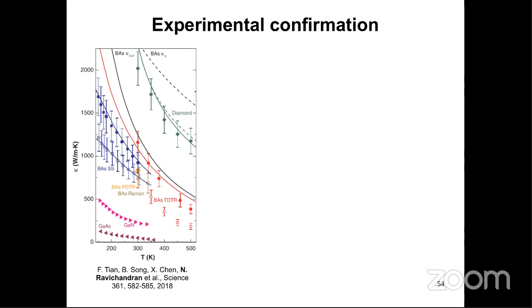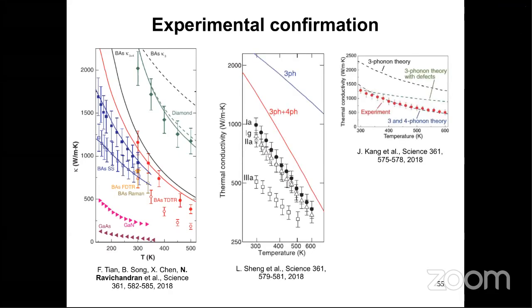So the black curve that you see here is a calculation, black solid line is the calculation from our work, including both 3 and 4-phonon scattering for boron arsenide. And this curve lies very close to their best samples, which are shown by the red circles. In fact, around the same time, there were 2 other competing groups who were also trying to grow boron arsenide crystals, and their experiments are also confirming our theoretical prediction that the thermal conductivity of boron arsenide is strongly affected by 4-phonon scattering. If you look at this middle figure here, the blue curve is the 3-phonon prediction, and their experimental curves match or roughly match the red curve, both in rough magnitude and also in the trend.